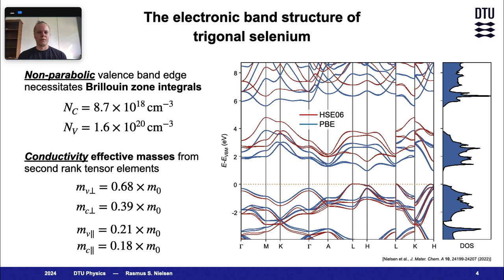The trigonal symmetry of the crystal makes the inverse conductivity effective mass a second-rank tensor, and by evaluating the tensor elements based on band curvature and symmetry, we get the following results. We do see the influence of the anisotropic nature of the crystal, but the effective masses are actually not as bad as one might think from just eyeballing the valence band curvature. Finally, it's important to note that the lowest energy transition across the bandgap is not direct, but the lowest direct transition is very close in energy to that of the fundamental bandgap. Therefore, one could call the nature of this bandgap quasi-indirect.